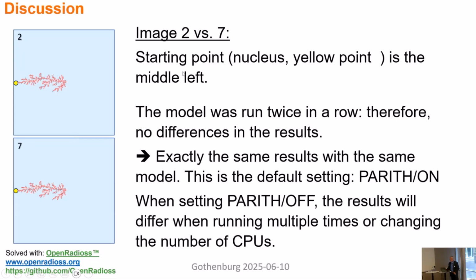This is typical for Radioss. This is a feature which means parallel arithmetic, which means if you change the number of CPUs or you do several repetitions, you will obtain exactly the same results. So we can guarantee this. If not, then there's a bug. Otherwise, you will get exactly the same results. Again, this is a feature. You can switch it off, then you will not get the same results. But by default, it is on.